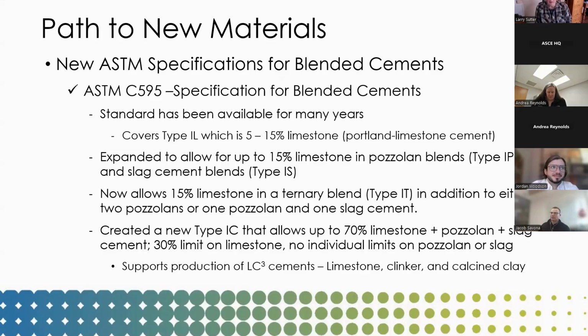C595, this is a blended cement specification. We've made many changes to this specification over the past couple of years. And there's a number of changes that have not yet been published. We're waiting to coordinate the publishing with ASCE, but the changes have been approved. And basically, probably the most major change is that we can now allow up to 15% limestone in what we refer to as a Type IP, a pozzolan blend, and a Type IS, a slag blend. Typically, in the past, we've only allowed 15% limestone in a Type IL cement, which many of you, I'm sure, are familiar with. But now 15% limestone can also be in an IP or an IS.